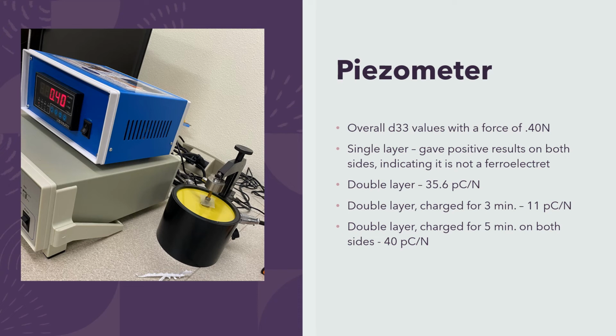We noticed when we polarized a double layer sample with the DC Corona treater for approximately 3 minutes, we got a D33 value of 17 followed by a negative 5 for the opposite side. This gave us a D33 value of 11. And when we charged a double layer silicone on both sides, we ended up getting an overall D33 value of 40.